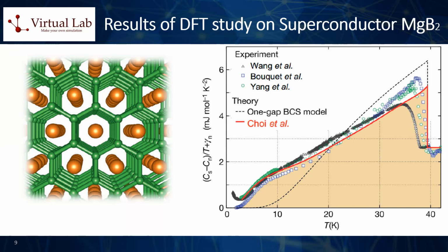The quantity plotted under the y-axis is derived by taking the difference between the heat capacity in the superconducting state of the material, labeled as Cs, and that in the normal state, denoted by Cn. It can be deduced from this graph that such theoretical first principles calculations, shown as the red line, are in relatively good agreement with the experimental behavior of the material.